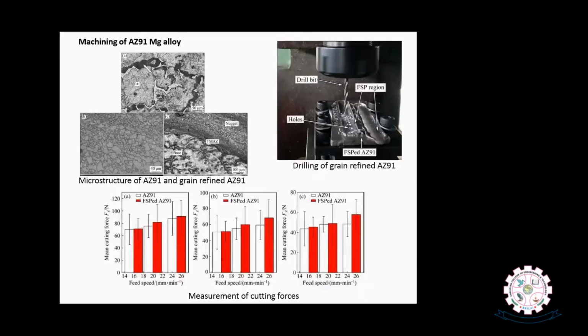We processed a magnesium AZ91 alloy by friction stir processing, and we developed a fine grained structure as shown in this diagram. You can compare the microstructure of the AZ91 magnesium alloy base material as well as the friction stir processed material. In the friction stir processed material, interestingly, the secondary phase was significantly decreased, and compared with the base AZ91 magnesium alloy, the friction stir processed AZ91 has given excellent grain refinement. Here we have two important factors. Grain size is very, very small, and the amount of intermetallic phase is also significantly decreased compared with the base material. So these two important factors have given better machining behavior.